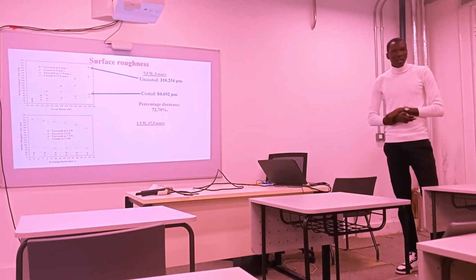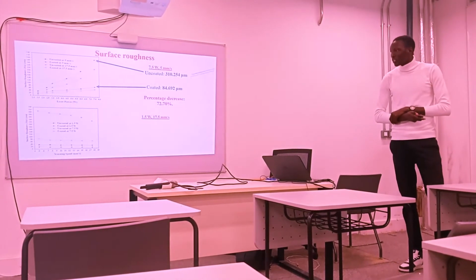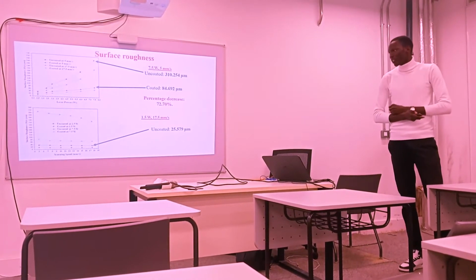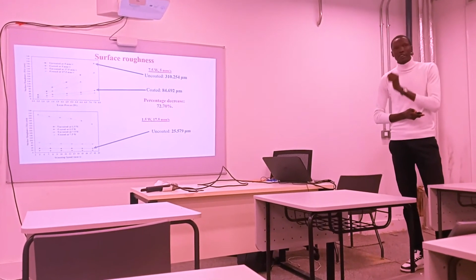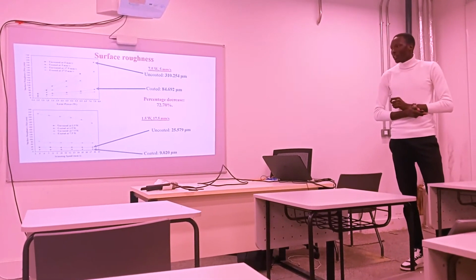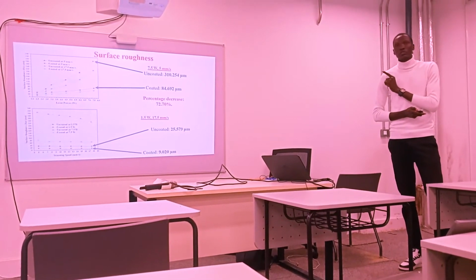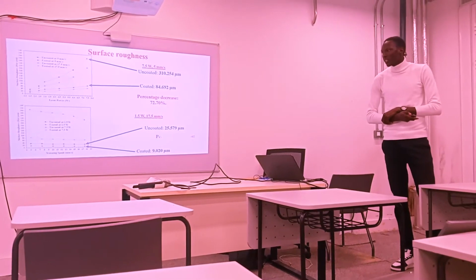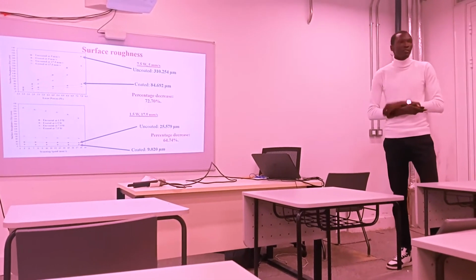At minimum power and maximum speed, for the uncoated, surface roughness was 25.579 micrometers. The value reduced to 9.020 micrometers for the coated, a percentage decrease of 64.74%.